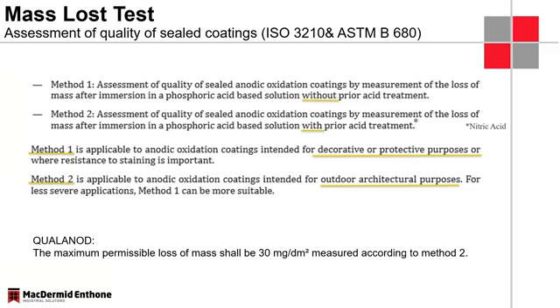There's another, different test for determining the quality of the sealed surface, and this is the mass loss test. It works in a similar way. We're actually submersing a known surface area in an acidic solution, which is normally a phosphoric acid based solution, and we let it react for a certain time. We take weight measurements of the components before the treatment and after this treatment, and we'll calculate the difference in weight, or the weight loss, for that particular surface area. And from there we can really calculate per square decimeter how much sealed surface we have actually lost. So for Qualanod, for the European specifications, they request less than 30 milligrams per square decimeter.